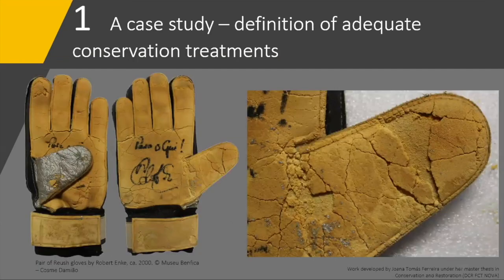Then, in a different case study, the identification was critical for the definition of an adequate conservation treatment. Here you can see a pair of gloves by Robert Enke from Museu do Benfica, which were showing advanced degradation and whose composition was unknown. At first, from an observation of the gloves, we thought the foam was made of polyurethane, as yellowing, brittleness, and crumbling were the main degradation symptoms observed, and no odor related to rubber or latex compounds was found.